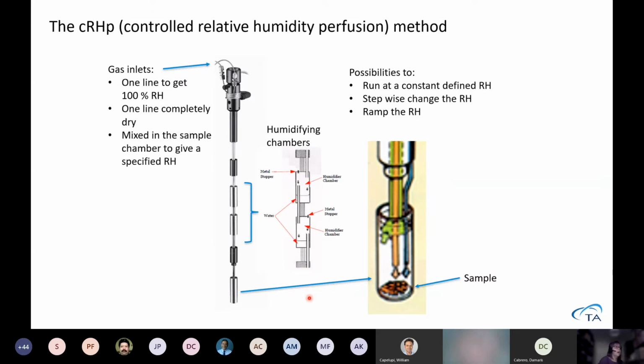Then we need to use the perfusion ampule, the RH perfusion ampule, where we can change the relative humidity. So this is an open system. It's one part of the microreaction system where we can manipulate our sample during the measurement. Here we will have two gas inlets. One will go directly down into the ampule where you have your sample that sits inside the calorimeter. The top part is outside the calorimeter.